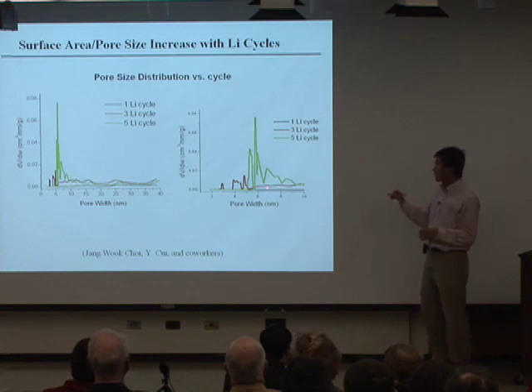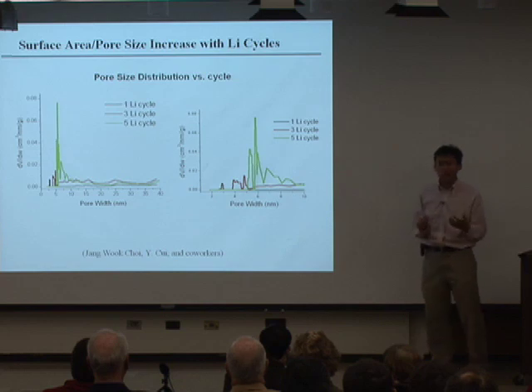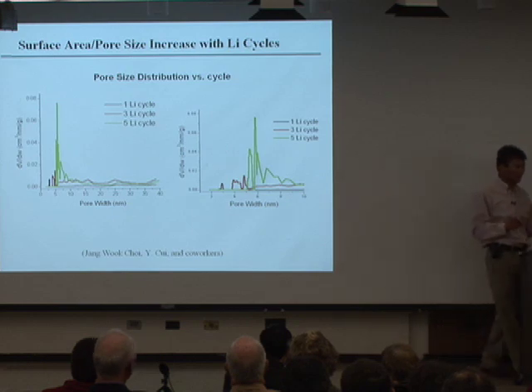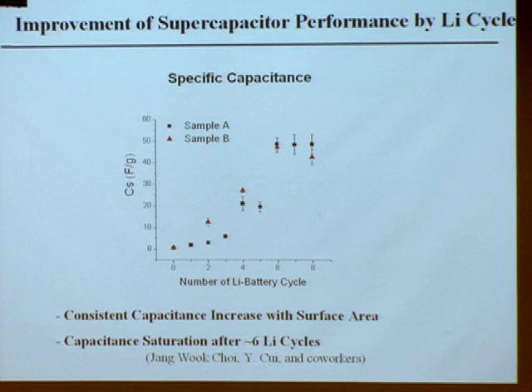Well, this is fascinating to me. This is the way you can use electrochemical cycling, depending on how you do it, how many cycles you do. You can control the pore size, allowing you to tune material properties designed for supercapacitors. So we have done supercapacitor measurements and figured out the capacitance, specific capacitance. When you do multiple lithium-ion battery cycling, you create pores, and then you do supercapacitor measurement. It really increases with multiple cycling, so you increase the surface areas accessible to those ions and the electrolyte.